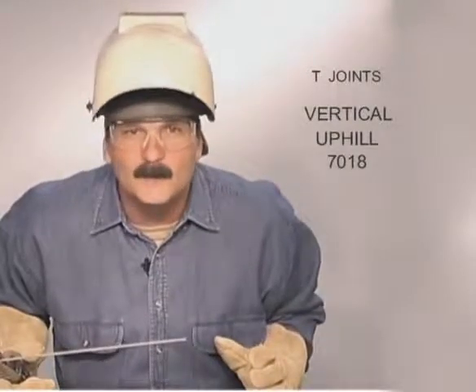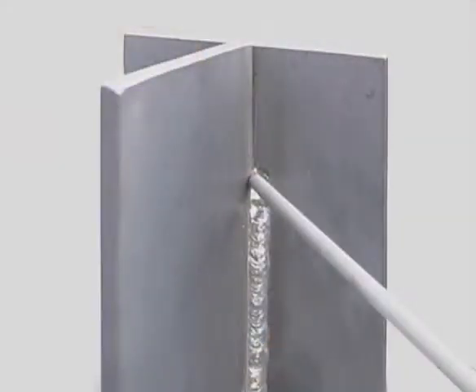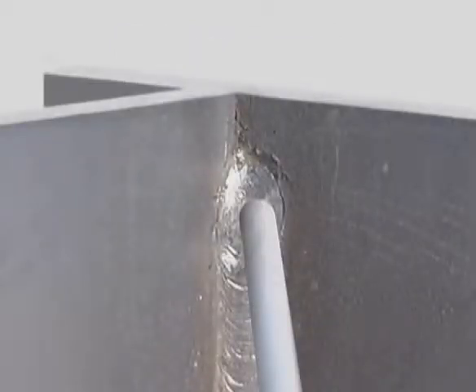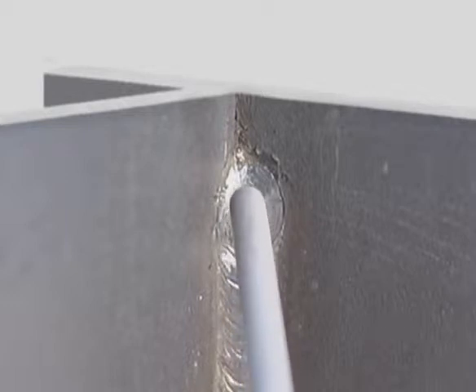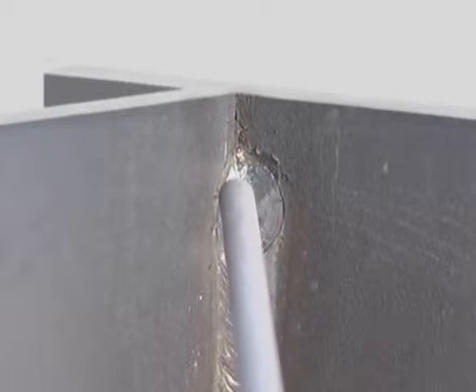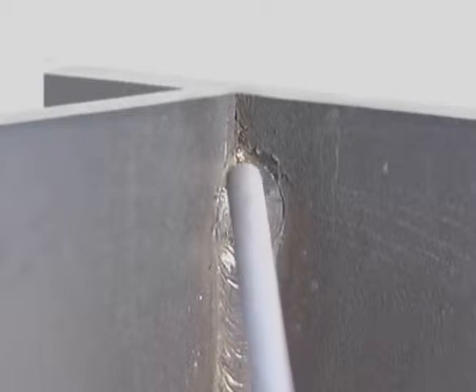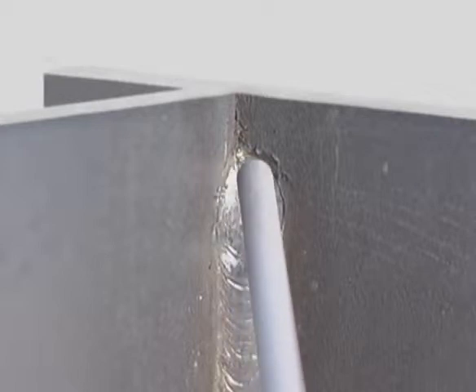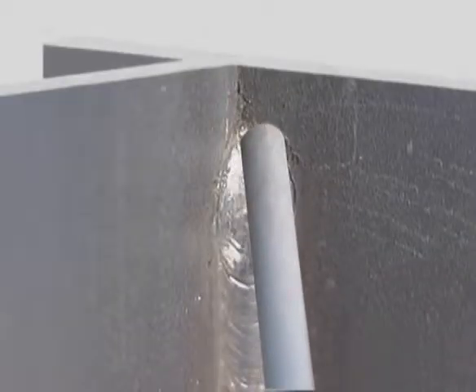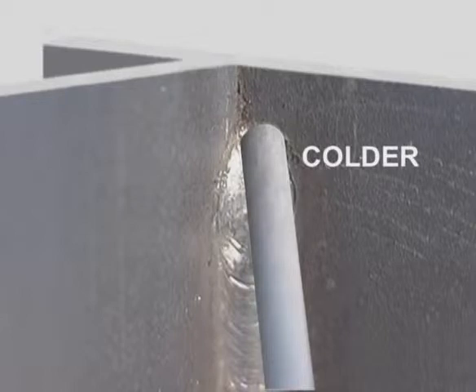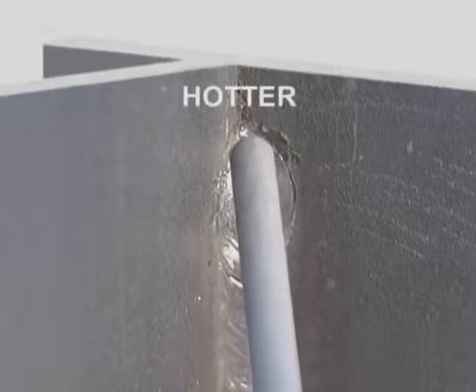7018 uphill will build weld faster. For the first pass deep in the corner, angle the rod up slightly. Pay attention to the arc gap, following the base metals into the corner and along the sides. This is very subtle. It's just a little movement into the corner as you're coming across, but jamming the rod into the sides cools the weld down, and long arcing across the center creates more heat.